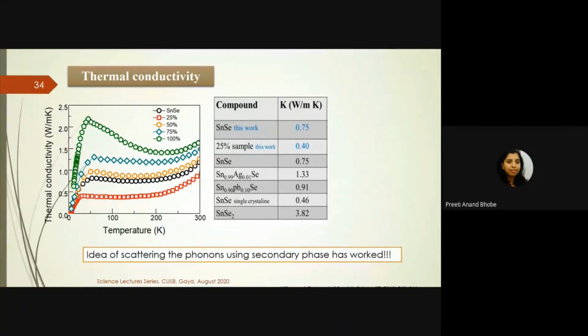Also, with a higher percentage of Se, some materials show higher thermal conductivity, but that higher thermal conductivity is still less compared to the pure SnSe2 phase. Pure SnSe2 phase would be around 3.8 of thermal conductivity, but here the maximum value we are getting is around 2.25. So compared to the pure phases of SnSe and SnSe2, we have got a reduction in the thermal conductivity. So our idea of scattering of phonons using the secondary phase seems to work.